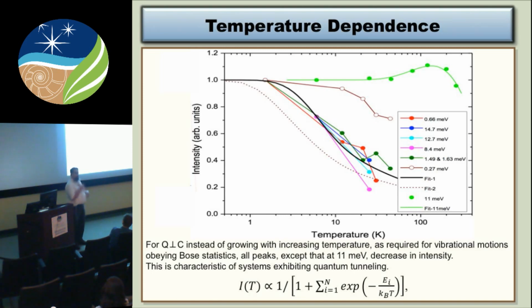This shows the temperature dependence of a number of different peaks. We see this one here is not one of the ones that decreased with temperature, but you can see we had 7 or 8 peaks that all showed the same thing. This kind of behavior is characteristic of 2 things. It can be either a magnetic effect or it's due to quantum tunneling.